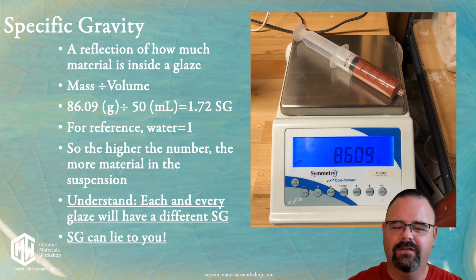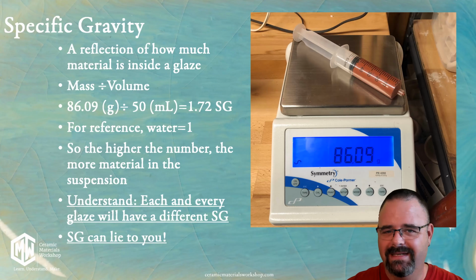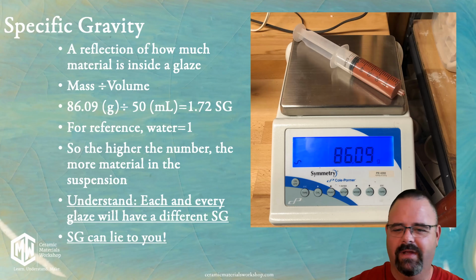I have used a syringe, and I have extracted 50 milliliters of glaze. I then weighed that syringe and found out how much material was in it. That was 86.09 grams. This, of course, had been tared, so the syringe is not in the measurement. To measure the specific gravity, I divided the 86.09 grams by 50 milliliters for a specific gravity of 1.72.